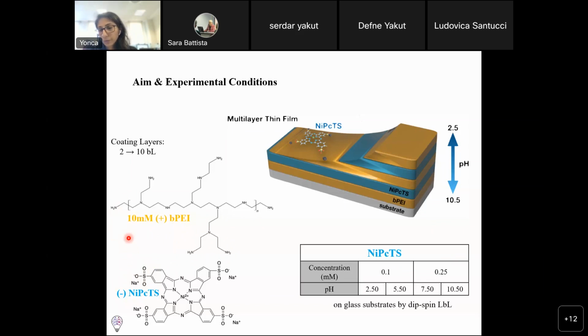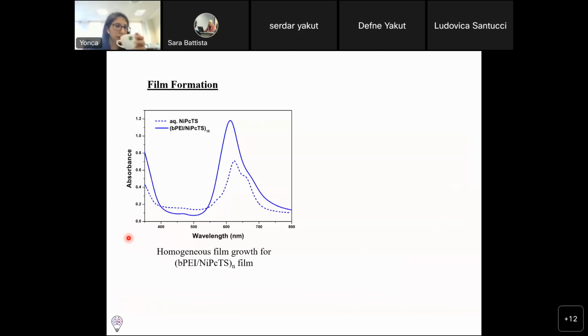So I've checked 2 different concentrations and 4 different pH values. So to start with, do we have any film? Yes. So by checking the photophysical properties by UV visible spectroscopy, we can confirm that the Q band of the water-soluble nickel phthalocyanine is visible in the solid form as well. And it's, as I said, around 600 nanometers in this case.